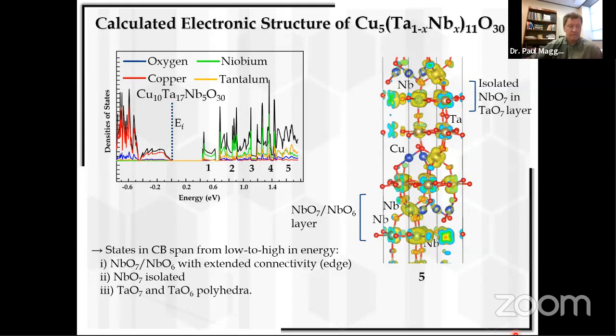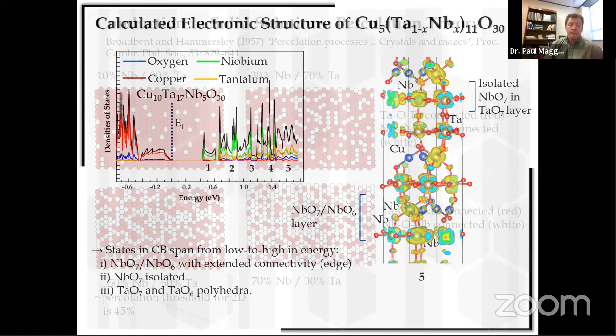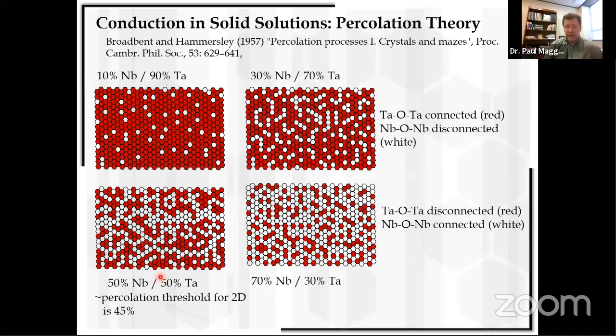Okay. So the states in the conduction band, from low to high in energy, go from the extended to the isolated niobate polyhedra, which is important. Because anytime you have a solid solution, you have a high amount of disorder, you need a mechanism that will delocalize those carriers onto the extended parts and keep them away from the isolated parts. But at what point, you may ask, does there arise an extended connectivity within that network?